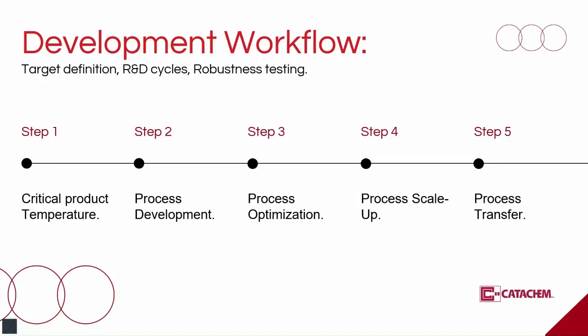Third, we run iterative R&D cycles with product probes and cycle analytics. The purpose here is to define a safe and efficient primary drying pathway and a validated secondary drying endpoint. Fourth, we apply robustness testing. Small variations in fill volume, load configuration, and parameter tolerances to confirm that the cycle is not fragile. A cycle that only works under perfect conditions is not a production cycle.